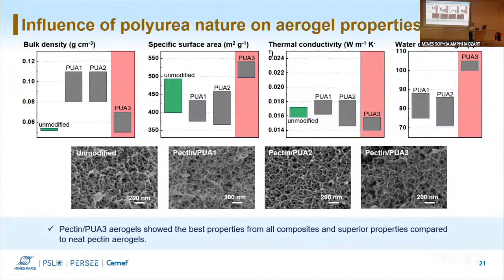Something that I didn't mention here, but it is in the manuscript, and is important now: for the third type of polyurea, for the same concentration of isocyanate used, we had a higher content. I rephrase: we had a higher content of polyurea for the first two composites rather than the third. So for sure, it's not the amount of synthetic polymer in the material. So this we take out.